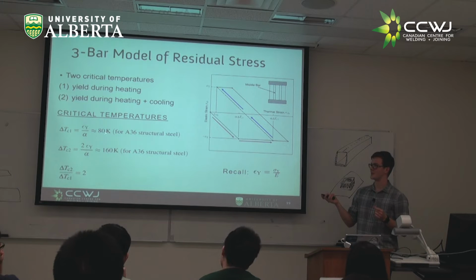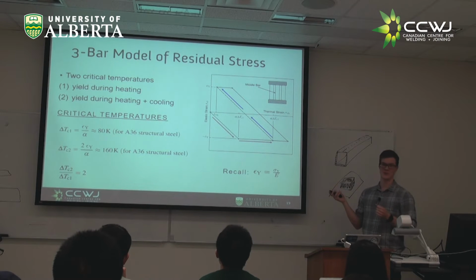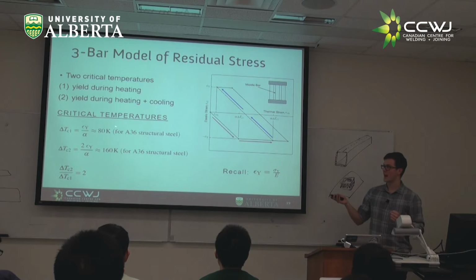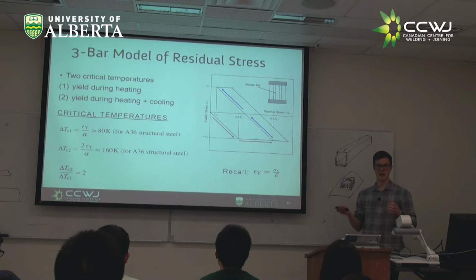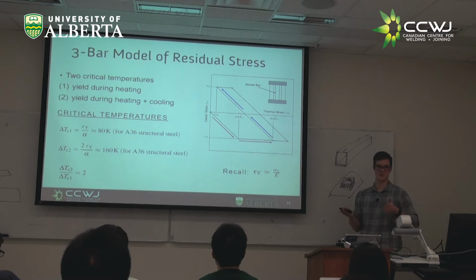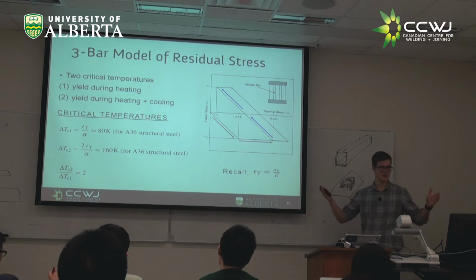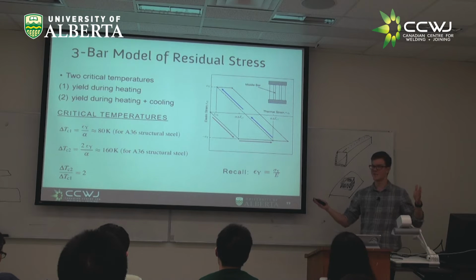So one of the things you can start to understand is why maybe this model where we ignore strain hardening, in fact, we've ignored temperature dependence of yield stress, seems to be okay. If we're worried about everything over 80 degrees Kelvin, you can imagine that the region where we have stress is huge compared to the region of our weld, compared to our heat affected zone. So all of the really complex material changes, whether it's phase transformation, whether it's melting, whether it's the fact that your properties are changing at high temperatures, those are all going to happen, and they're all going to affect the stress you have in a region of your weld. But the total region you care about for stress is going to be so much larger that as a first approximation, you don't necessarily have to worry about those effects.